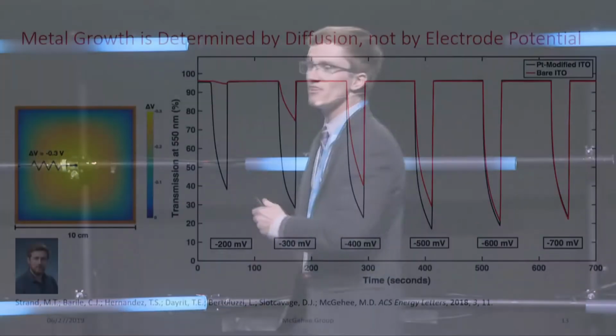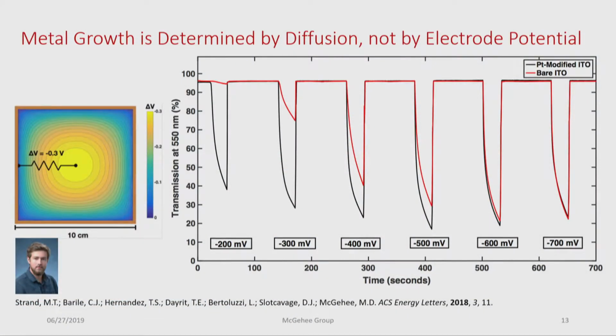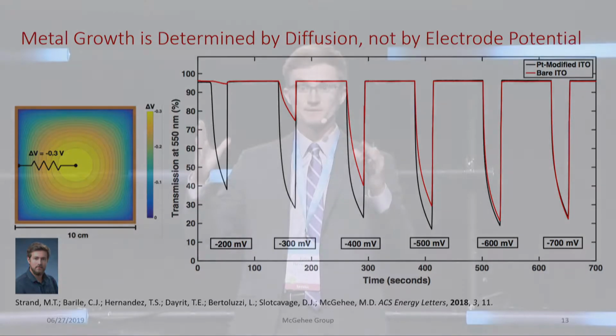What I mean by that is that there was this great study done by a colleague in my group, Michael Strand. And what he did was he showed that in a 3-electrode half-cell experiment, if you take a bare ITO surface in our bismuth copper electrolyte, and you vary the potential applied to this electrode, you can see that as the potential is dropping, the contrast ratio is also continuing to decay, which is exactly what we saw in our large-scale window where metal is only preferentially plating on the side.